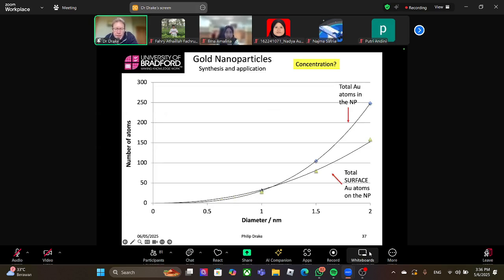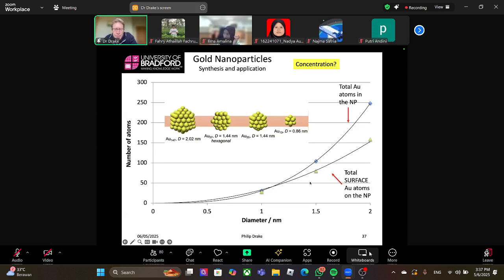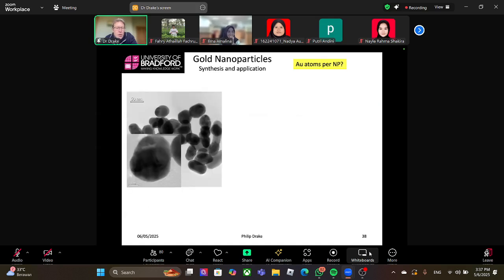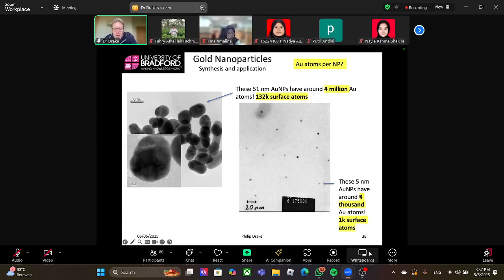And as we get down to 1 nanometer, you can see at 1 nanometer, all the atoms are surface atoms. 1.5 nanometers, you've got some in the core and a lot on the surface. And it's the ratio of the surface to core which is important. So a 0.86 nanometer particle is about here somewhere. All these are surface atoms. With the bigger particles, you've got core atoms which are masked and the surface atoms involved in the chemistry. So the big particles, we know there's about 4 million gold atoms and about 132,000 surface atoms. Small nanoparticles, we know there's about 4,000 atoms and about 1,000 surface atoms.